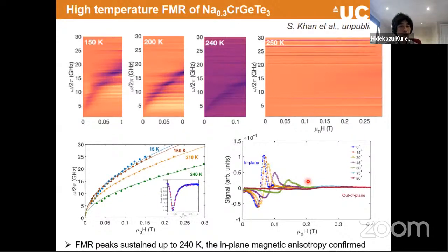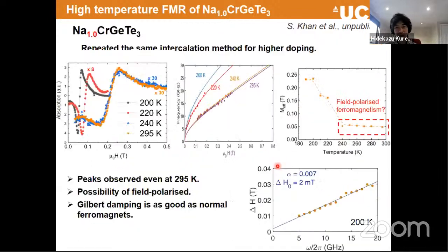So we can tell that when we dope, it definitely promotes the magnetism up to really high temperature. And I also show that this is not only 0.3, but this is the 1.0 doped case. It's a heavily doped case. We can maintain the resonance up to 295 kelvin. I thought that's really exciting news. But by looking again at the resonance field as a function of the frequency, we can tell that it's something strange, because when we reach the higher field regime, this value of the effective magnetic field, which is pretty much proportional to the saturation magnetic moment, is floating rather than changing as a function of temperature. So we think that at this regime, long-range spin order is gone, but somehow we maintain short-range spin order, and they still observe some effective magnetic moment inside, similar to an ESR response.